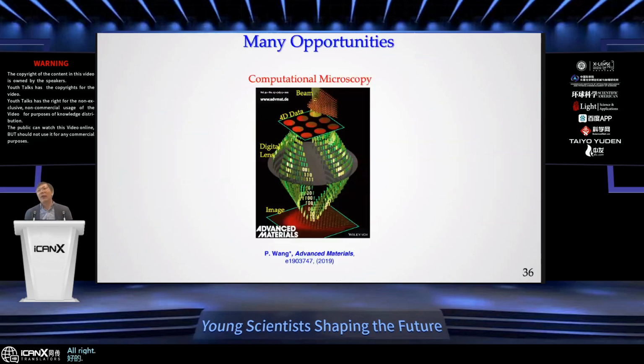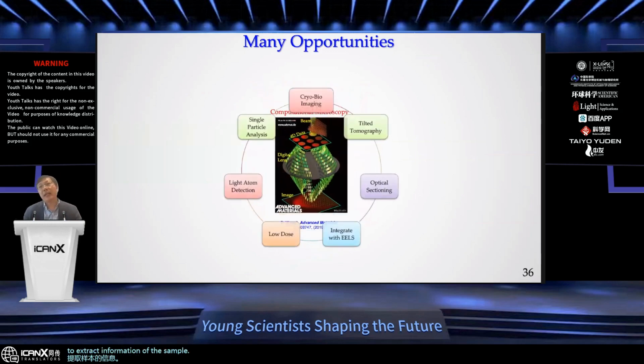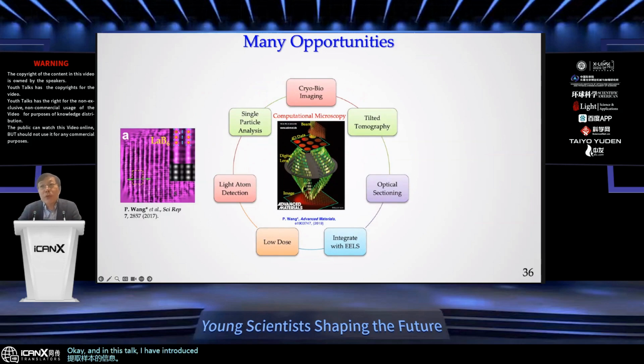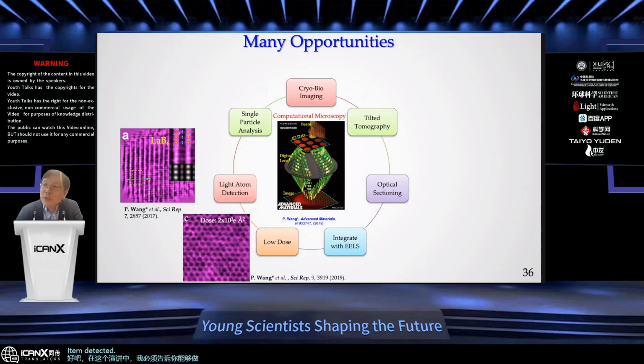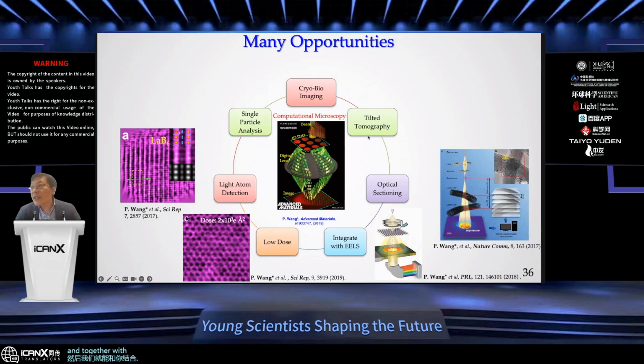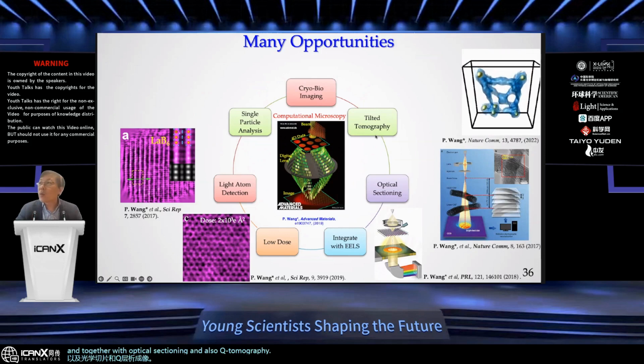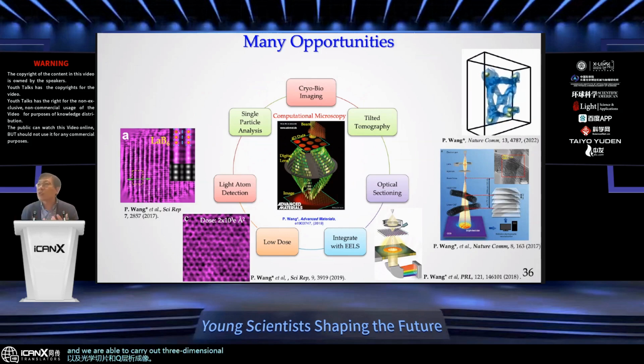All right. Okay. So what we would like to say is that with an ultra-fast detector, we are able to scan the beam along the sample to form this four-dimensional dataset. And rather than using physical optics, we are now using so-called digital lenses, using computer algorithms to form an image and extract information about the sample. In this talk, I have told you about how we are able to do light atom detection. We also can do low dose imaging, and we are able to combine with EELS together with optical sectioning and also tilt tomography, and carry out three-dimensional reconstruction.